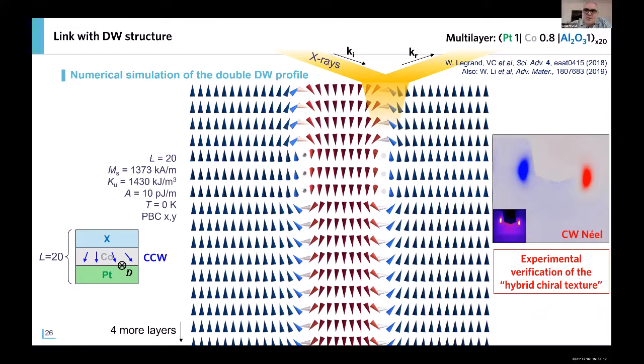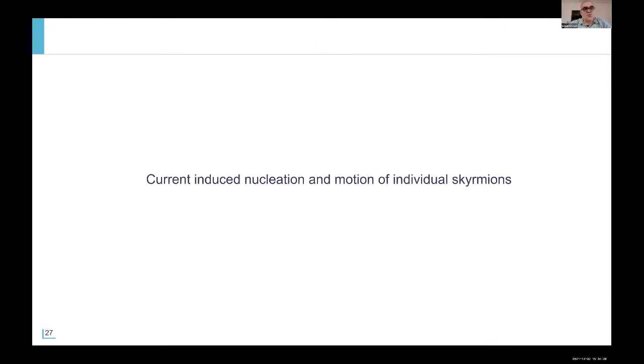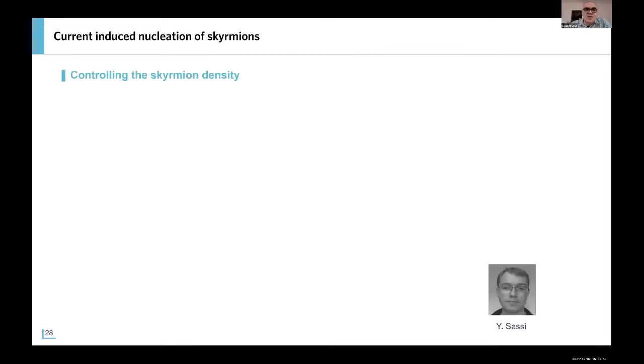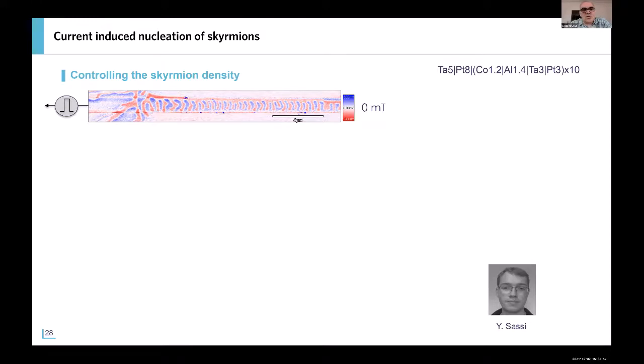I will show at the end of the seminar that we try to go beyond this and create really three-dimensional texture. So let me say a few words now about the recent results on the nucleation and motion of individual skyrmions. This is very important, as I said, for the potential application to use this fascinating property of skyrmions, but to make them mobile. So this is the main part of the PhD work of Yannis Sassi. And what we did recently was to try to control by a current injection the density of skyrmions. And for that, we focus on the multi-layer system that is platinum, cobalt, aluminum multi-layers.